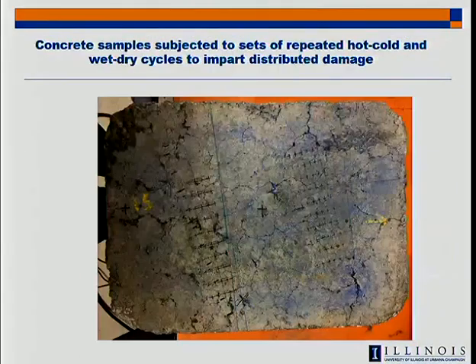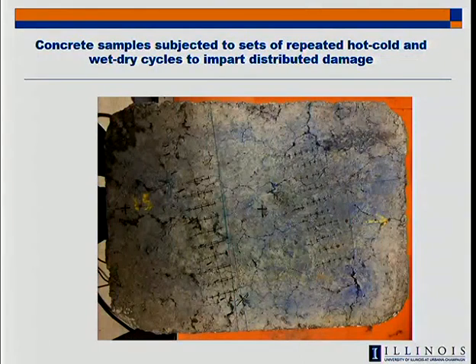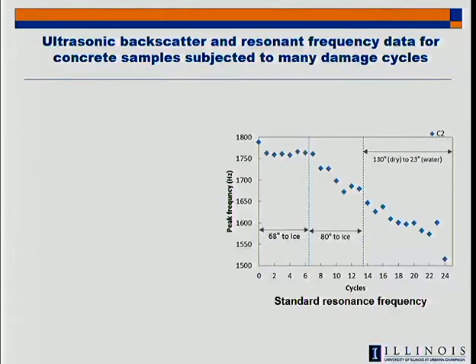And so what we did is that we increasingly cycled this concrete to put more damage in it. And as you see, as we put more cycles here, different kinds of cycles, hot, cold, wet, dry, that causes damage in concrete. By the way, rail ties are subjected to hot and cold cycles and wetting and drying cycles. So this is a realistic damage mechanism for concrete of any sort. We see that this standard laboratory way, the best way to measure damage in concrete, shows that our cycles are definitely causing this damage to increase.